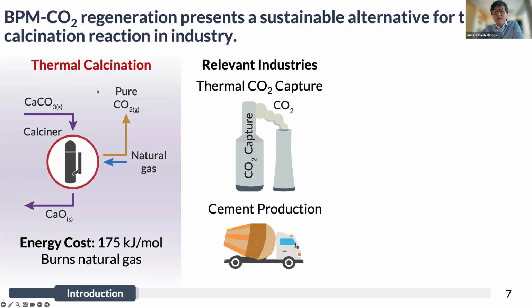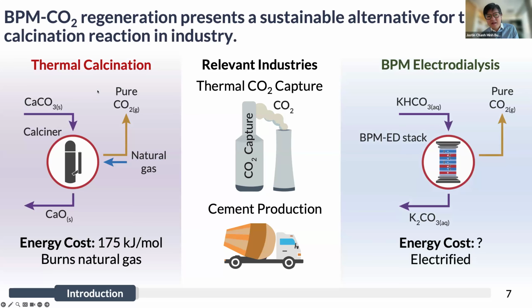involves this calcination reaction. We can use a bipolar membrane to basically circumvent this entire process, where instead of using this high temperature calciner, we can apply voltage and we can use acid to strip CO2 from our bicarbonate solution. And then we can use base to regenerate that carbon capture sorbent. And so we can basically use the bipolar membrane as a means to replace this high temperature reaction with a low temperature electrical process. And this has an energy cost that at the moment, when we started my PhD, was not really well quantified.